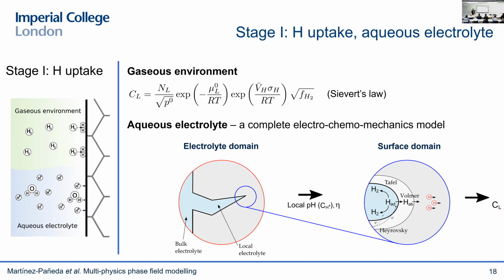So starting with hydrogen uptake. Here the goal is to develop models that are able to predict the uptake of hydrogen, so they quantify the ingress of hydrogen, for a given environment, what is the hydrogen content at the surface. And in gaseous environments, the picture is relatively simpler. So under certain assumptions and conditions, you can come up with closed form solutions that relate the hydrogen fugacity or pressure with the hydrogen concentration on the boundary.